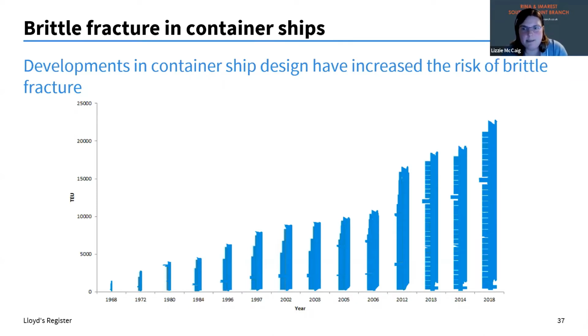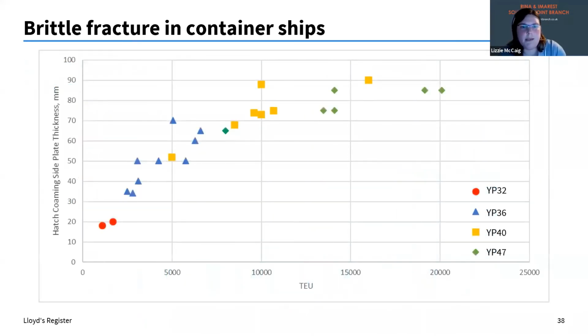What this has meant is that the required plate thickness for the upper hull girder has increased dramatically because the stresses have increased a lot. And in order to reduce that plate thickness, the use of high tensile steels has increased. You can see here a plot showing hatch coaming side plate thickness, and these are the different steels. Down here we've just got YP32, which is high tensile steel, but not that high tensile. We move on to YP36, but by the time we get up to 20,000 TEU, they're using YP47. That's got a yield stress of 460 newtons per millimetre squared. So the trend has been, as the ships got bigger, to use higher and higher tensile steels.